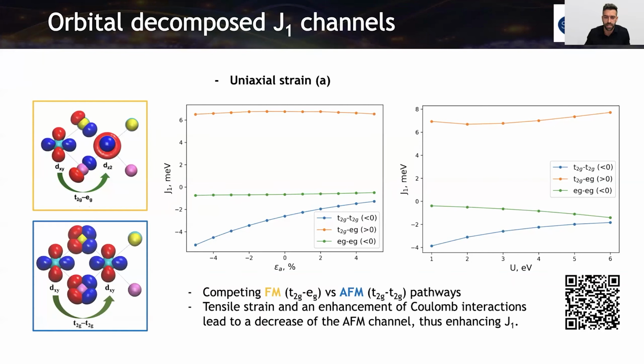That when we take the crystal field, we have an assumption of a perfect chromium 3+. No, I'm sorry, but that's not correct. Crystal field has nothing to do with ionicity. If your octahedra are perfect, no matter how covalent your bonds are, you always have a clean separation into t2g and eg. But I can see that in your case, the geometry of your octahedron is not perfect. So that might be the case.